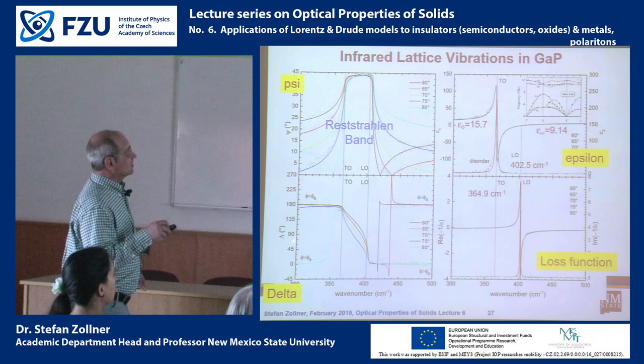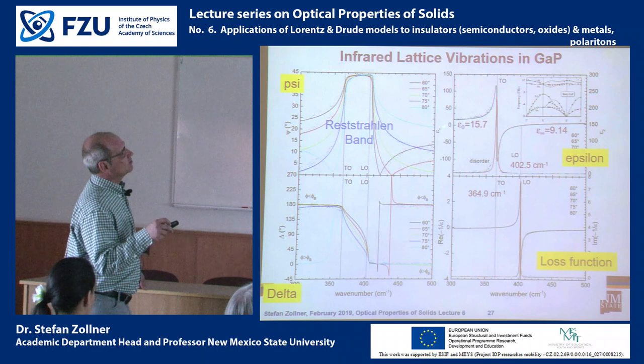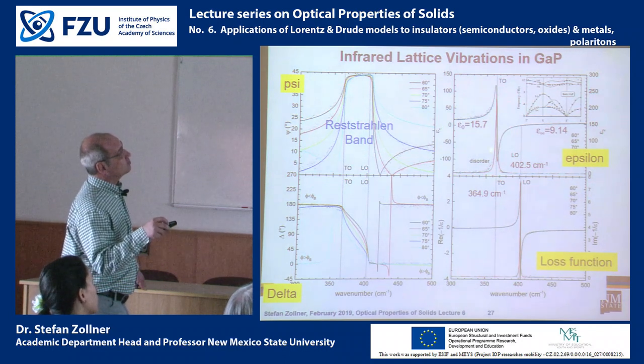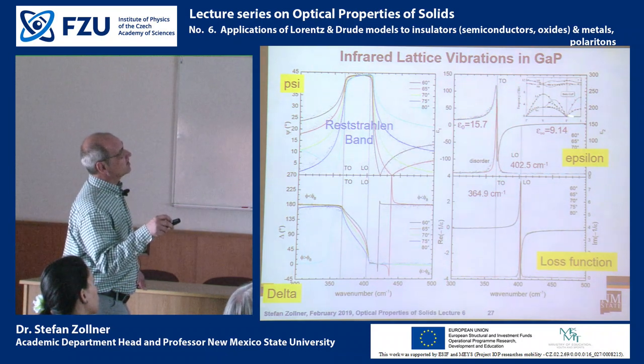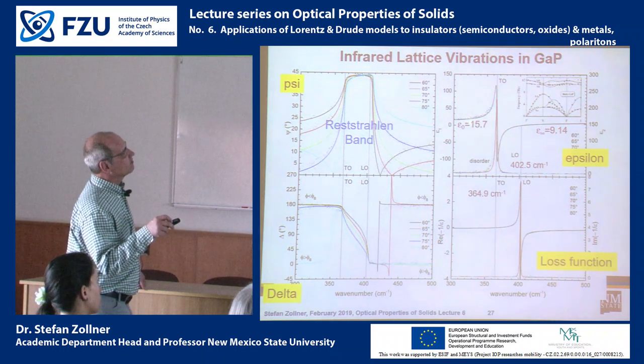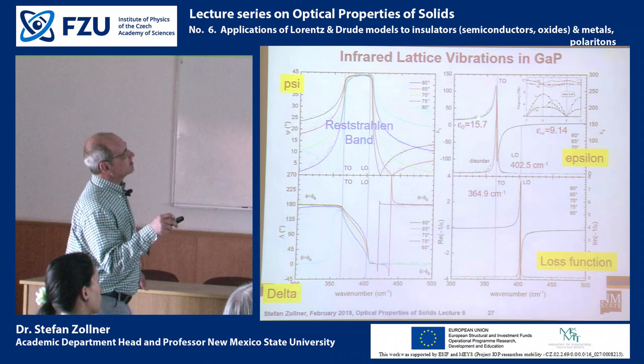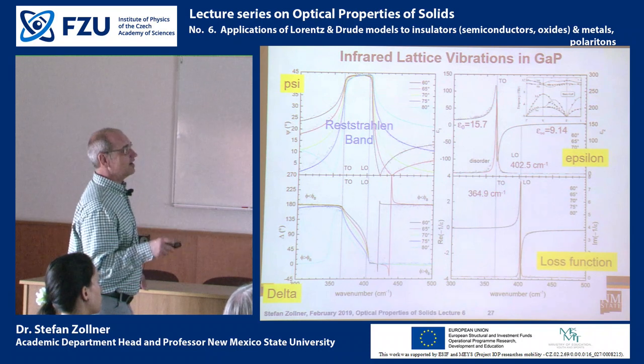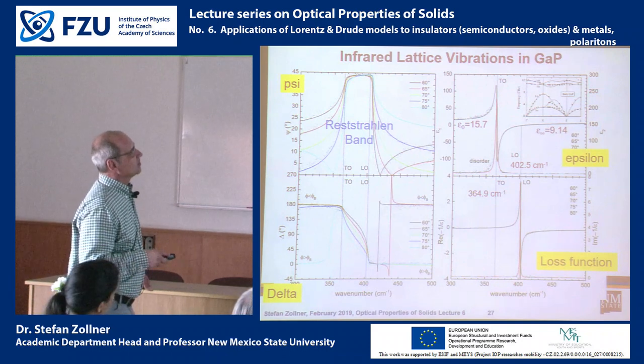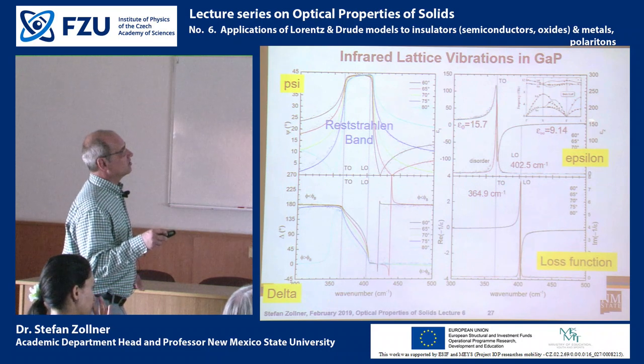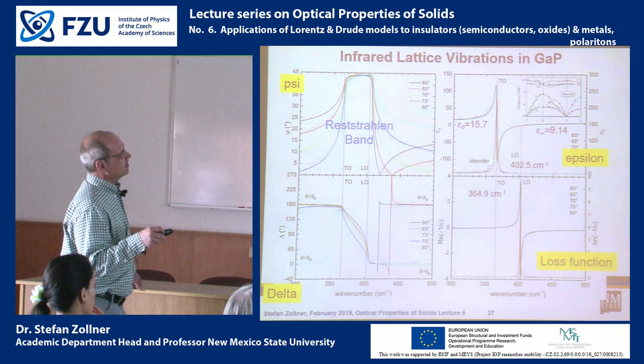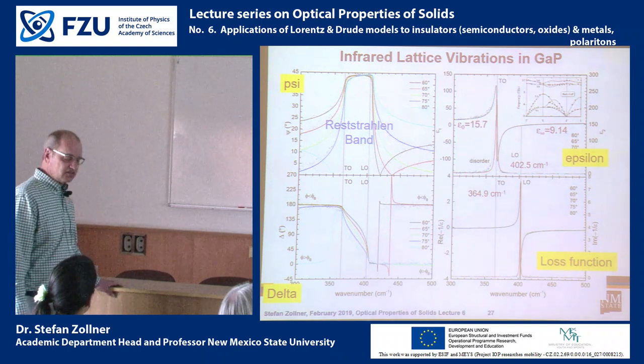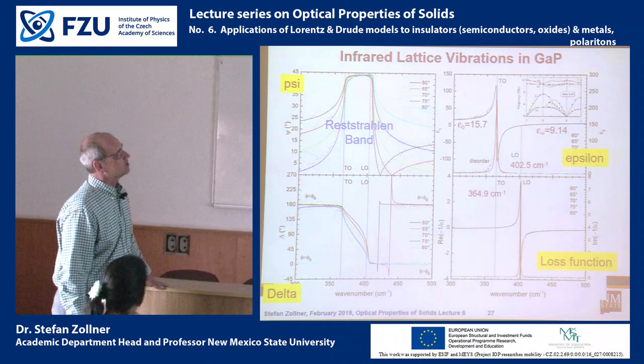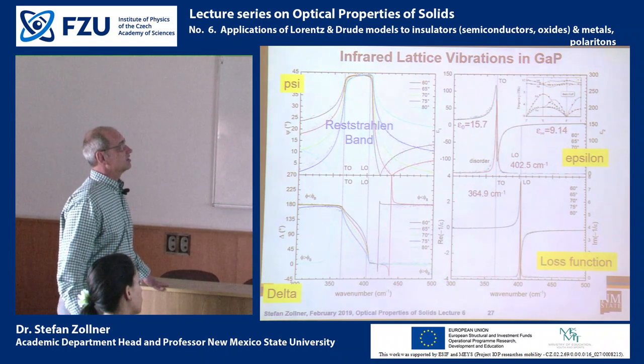So from the ellipsometric angles psi and delta, we can calculate the dielectric function without modeling. And what we see here is an absorption peak shown by the red line and this derivative-like structure for the real part, which is shown by the black dots and by the black line. And we see that at low frequencies, we get the static dielectric constant, which is 15.7. And at the higher frequencies, we get this high-frequency dielectric constant, which is 9. So as stated before, the static dielectric constant is always larger than the high-frequency dielectric constant. There is a little bit of a deviation between the model and the data just below the TO oscillator. And typically, one describes that with a little bit of disorder in the lattice, which gives us an asymmetric peak shape.